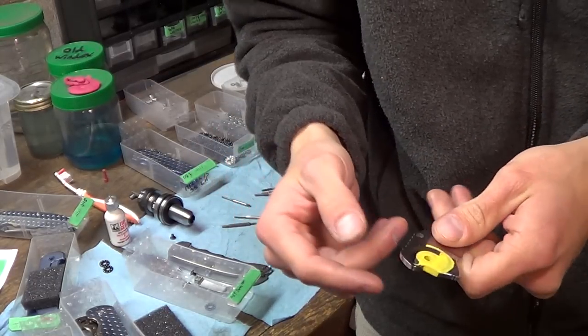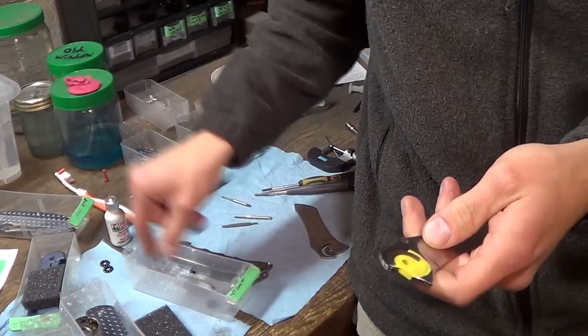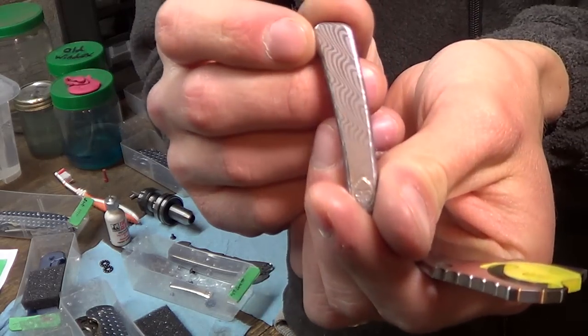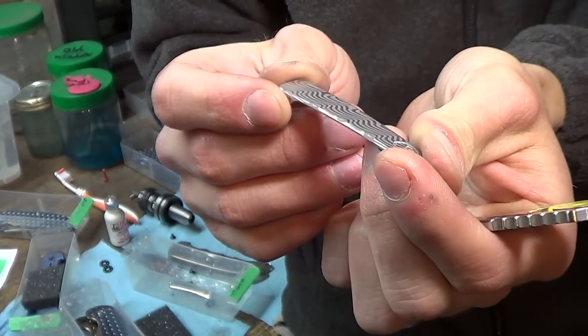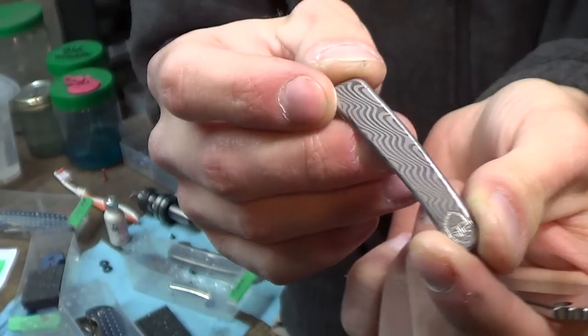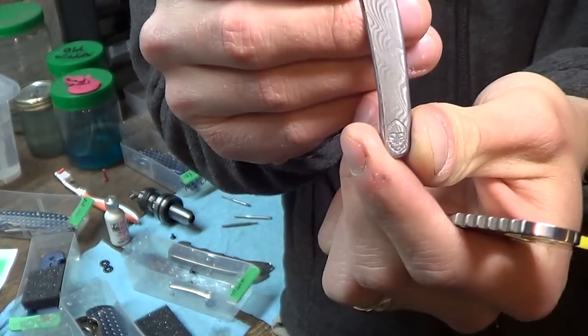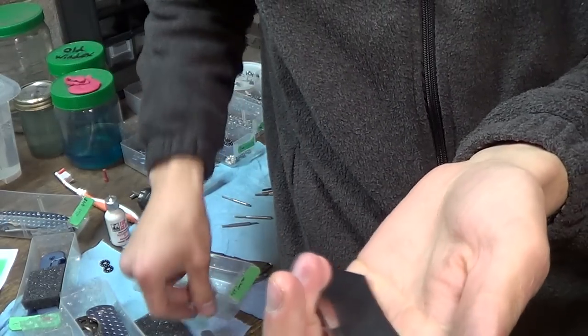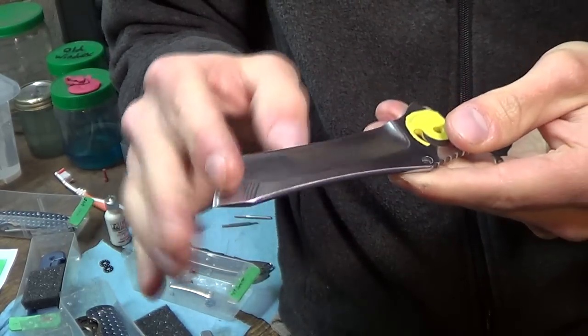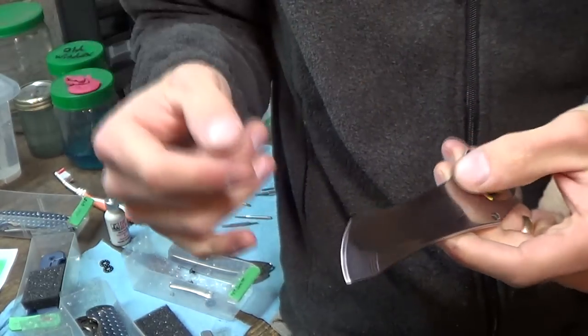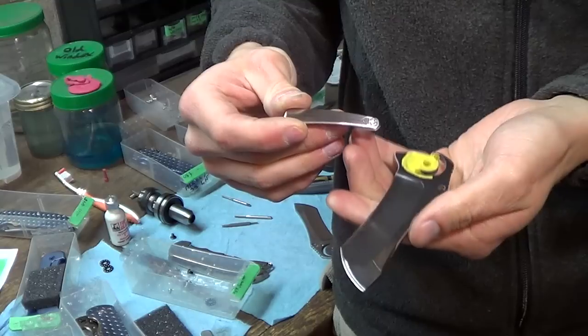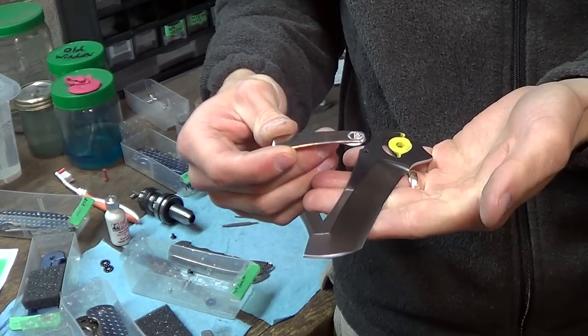Hopefully nail polish is strong enough to hold up to the ferric. I'm going to use ferric chloride this time, not muriatic acid. For reference, this guy was etched with muriatic acid for maybe 10 to 20 minutes. Looks really cool, but there's not a lot of contrast and the color difference could be better. I'm going to clean it really well and etch the pocket clip at the same time so they match. After I clean it, I'm just going to dip it in ferric chloride and leave it for a while.